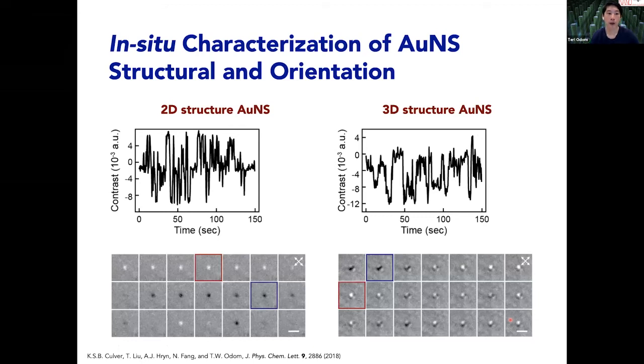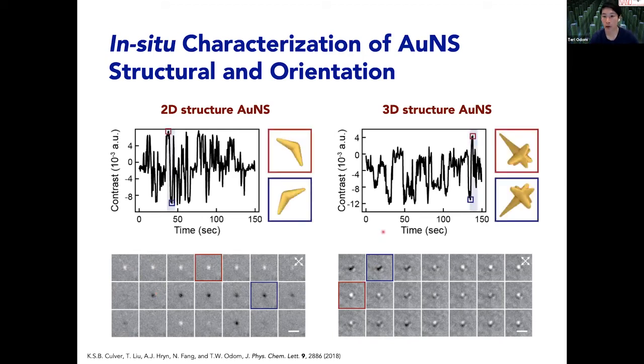And so we were able, for example, to differentiate between two-dimensional and three-dimensional structures. So the two-dimensional structure looks like a rod, and it's just completely white, bright, or completely dark, depending upon relative orientation. And then similarly for the three-dimensional structure, you notice that there are these lobes, partly because the structure is more complicated. But what's nice is, and we've just published this in ACS Central Science related to this three-dimensional structure and this type of two-dimensional contrast. So it's a really nice way to say, okay, in real time, we can determine what the local orientation is, which is hard to do because these particles are about 50 nanometers in size, so deep subwavelength.